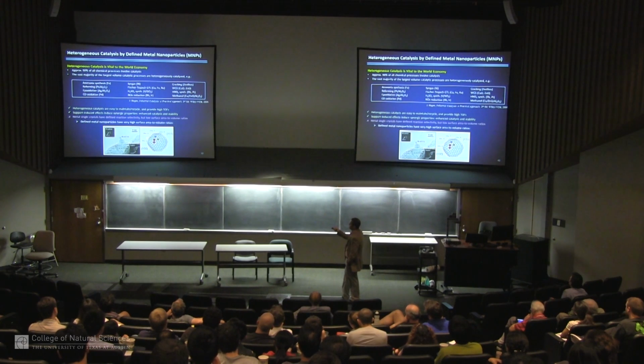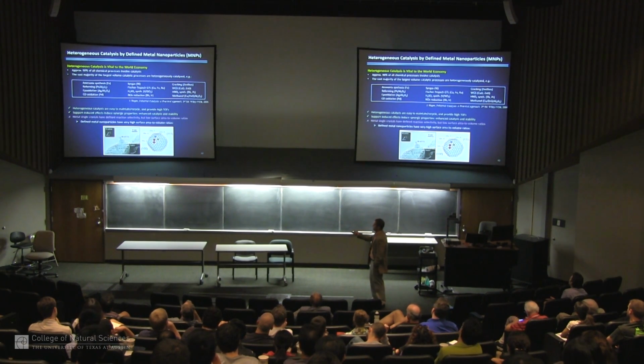And the reason why this is important is that although heterogeneous catalysts are very easy to maintain and recycle because they're always in a different phase, a problem with these catalysts is selectivity because they're metal surfaces and the selectivity is lower than a well-designed single-site catalyst. And one way to improve upon selectivity is to control the surface ordering of the atoms, because in a crystalline metal you can have different atom arrangements or packing on the surfaces that are exposed in different ways. And it's well known from many surface science studies that a single metal that's a pure crystalline metal can have a different reactivity for a simple reaction based on the type of metal surface that's exposed. And that's because the packing density of atoms on the surface is different on different lattice planes. And so that results in changes in the chemistry.